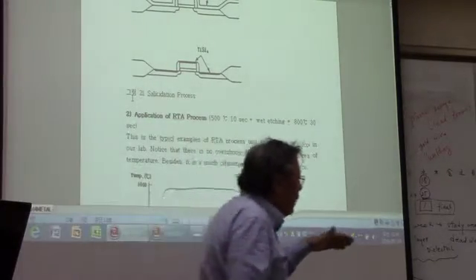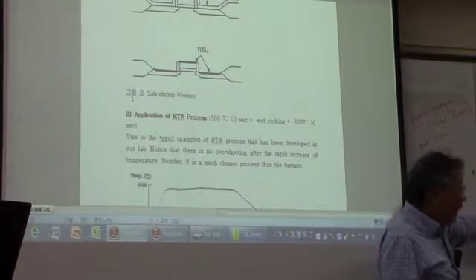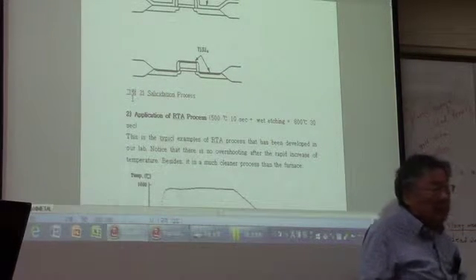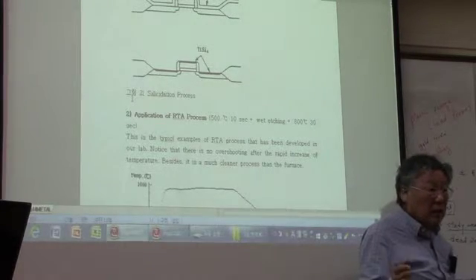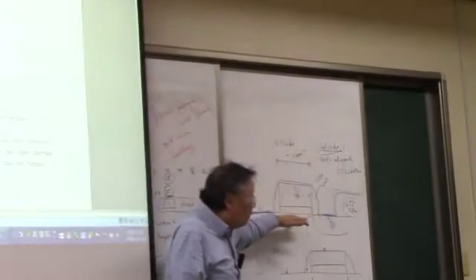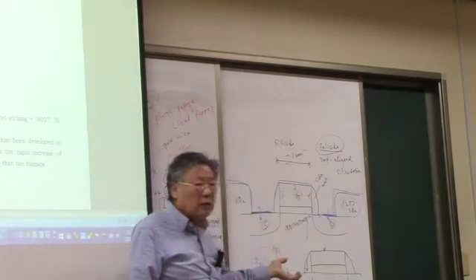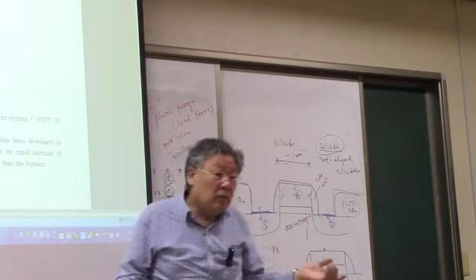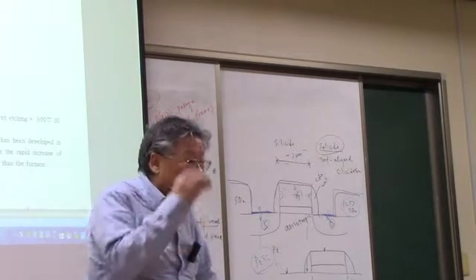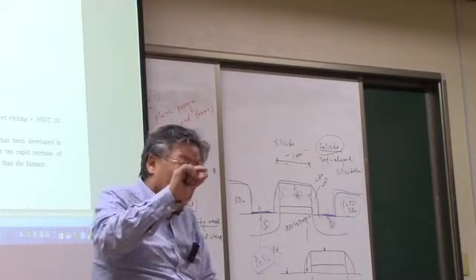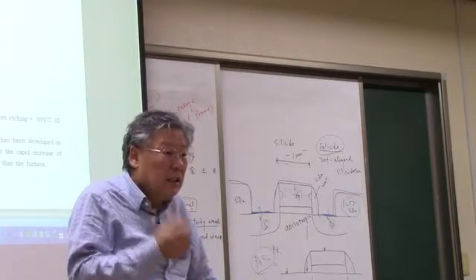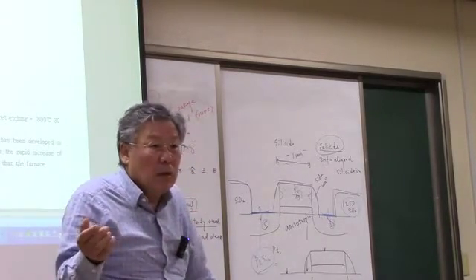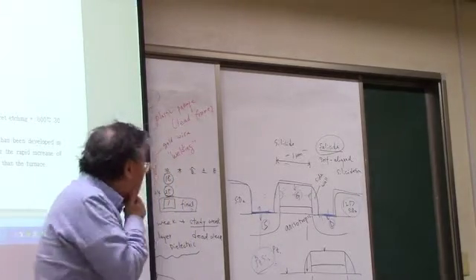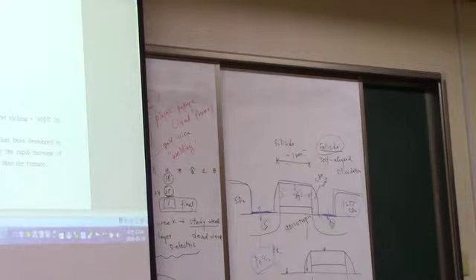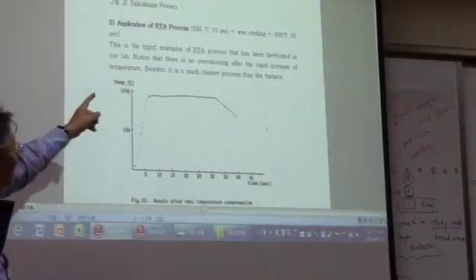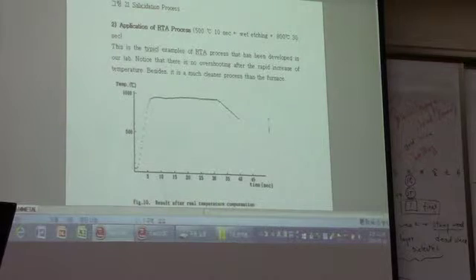A very thin film of platinum, cobalt, nickel, transition metals, and that thickness is several hundred angstrom only. Okay, so when those metals are deposited and you heat it up at 900 degrees centigrade or 950, then the reaction will happen in a minute. So, because the metal layer thickness is not that thick, the product, silicide, is not going to be thick. It's about 100 angstrom or so. So, in practice, in the industry, they use RTA, rapid thermal annealing, for the silicidation process.